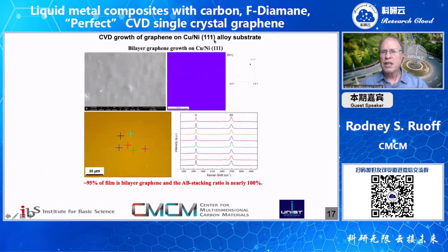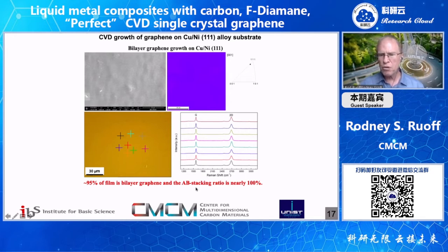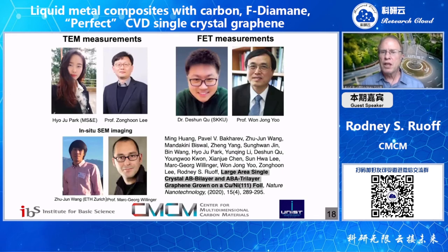When Ming upped the nickel concentration — around 20 or 23 atomic percent — he could get mostly bilayer graphene, which was almost entirely AB-stacked. This happens because we have a single crystal substrate with epitaxial growth occurring on it. These colleagues contributed to that work, published as shown here, and the Raman maps again show very high quality.